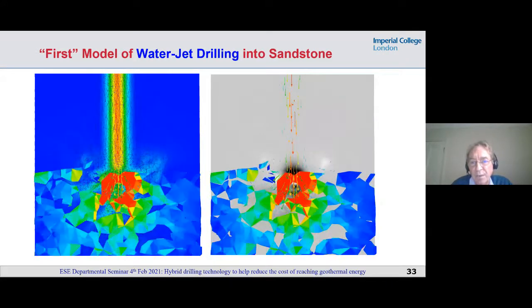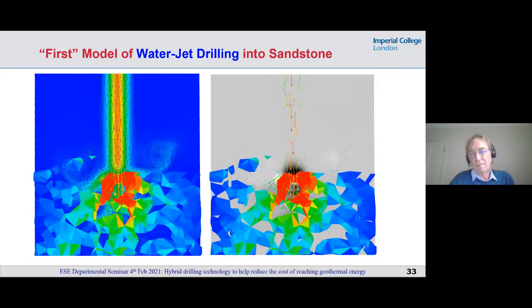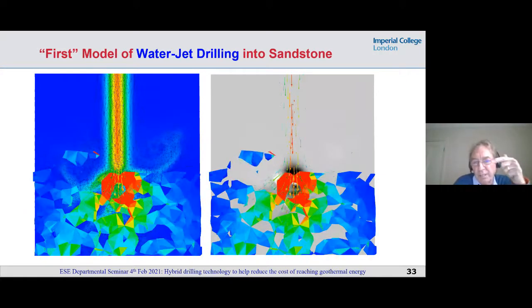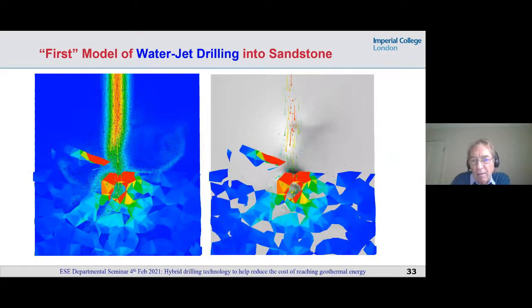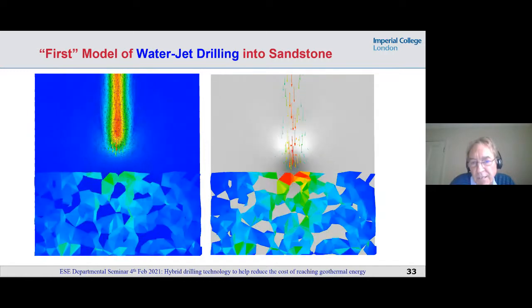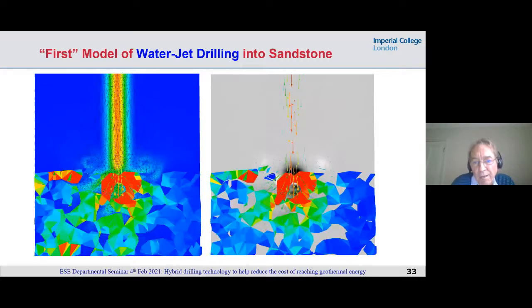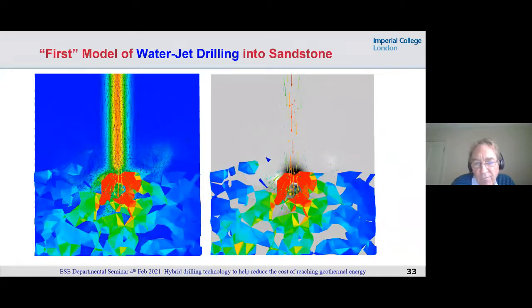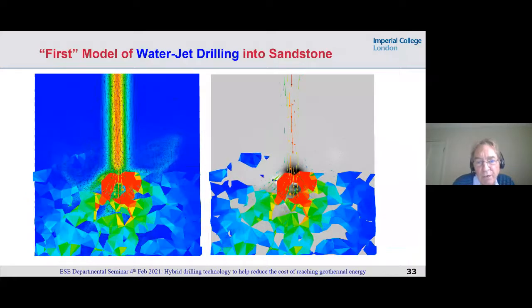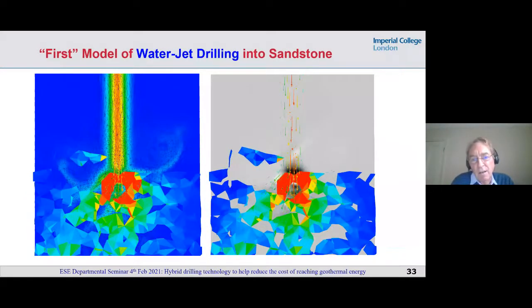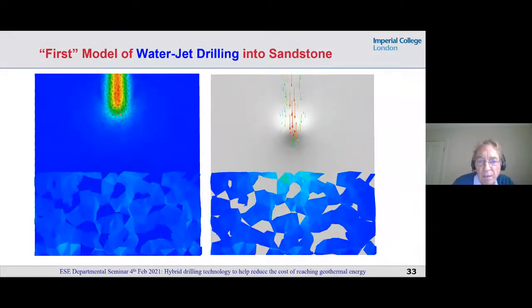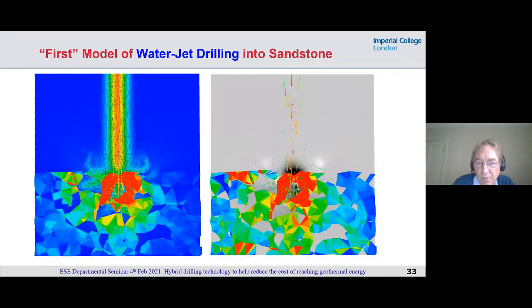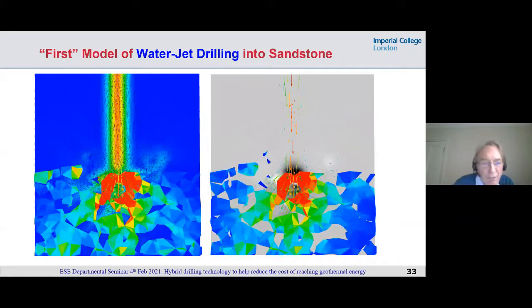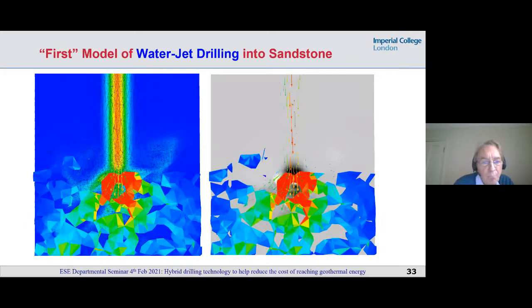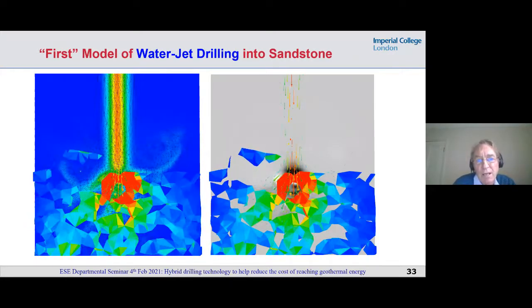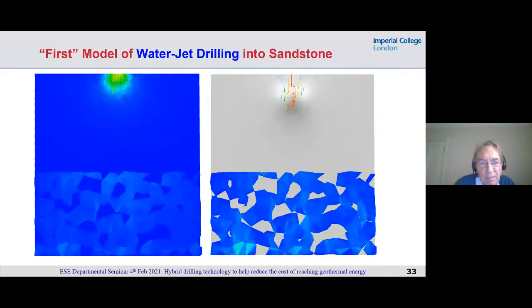And you can see that hammerhead effect pulverizing the granular structure. And when we watch it again, you can see early on that fluid pressure exerts itself between and gets into that pore space on that left-hand shoulder region and starts at very high velocity prising off along a grain boundary and ripping away that grain that goes spinning off into the fluid, that what was a stationary fluid but is now very turbulent. So you can see all of that fluid pressure captured inside the granular system and breaking those fragments. This is the first time we've had any model that's showing that mechanism in a sandstone.